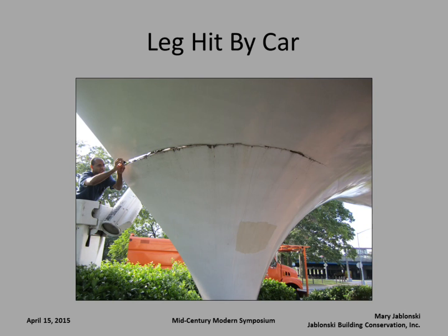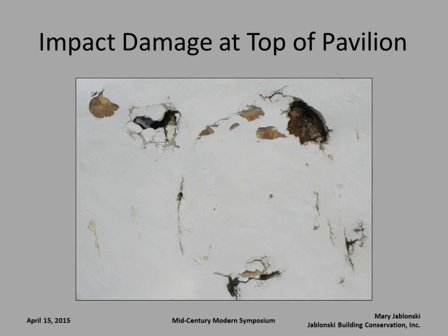But this is not the only problem. We have impact damage. The most severe damage was caused when a car hit one column leg, and you can see the crack at that joint is quite large. There's also the problem that people have been climbing up the pavilions, skateboarding on top of the pavilions, riding their bikes up the legs, kicking soccer balls on the interior. And here's a case where somebody probably was on their skateboard and fell, and you can see where their elbows came down. They were quite lucky they didn't fall down.